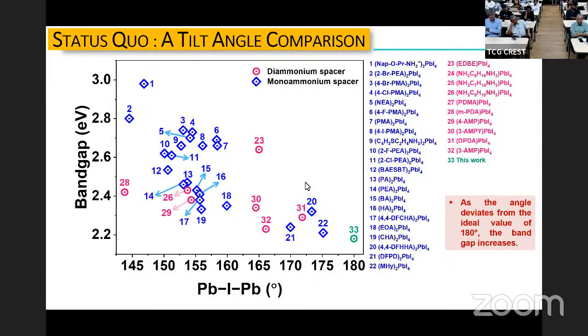I told you that there's an iodine that is shared between every two Pb. If that angle is absolutely straight, we understand very easily that the electron can hop from lead to iodine to lead very easily. As that angle bends away from 180 degrees, that hopping becomes less efficient, less facile, simply because the symmetry of the wave function that allows you to hop from this side to that iodine is not exactly the same symmetry that will allow you to go from the iodine to lead. So effectively, the hopping between lead and lead becomes smaller, so the bandwidth decreases, and when bandwidth decreases, the band gap increases. And that is exactly what you're seeing.